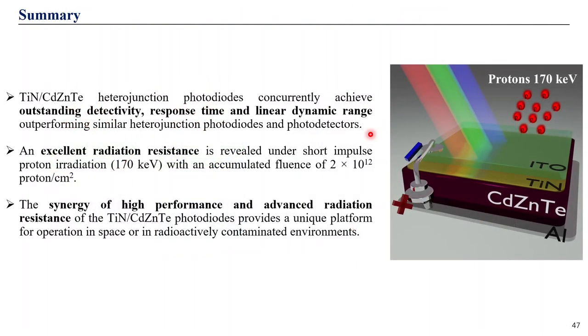So summarizing, we propose this new titanium nitride cadmium zinc telluride heterojunction photodiode, which simultaneously achieved outstanding detectivity, response time, and linear dynamic range, indicating that it's a really high-performance device, outperforming equivalent photodetectors based on compound semiconductors. We have proven experimentally that, as expected, this heterojunction possesses high radiation resistance, and the synergy of this high performance and high radiation resistance results in the possibility for applications in space and other radioactively contaminated areas.